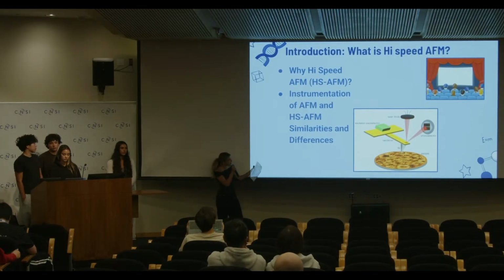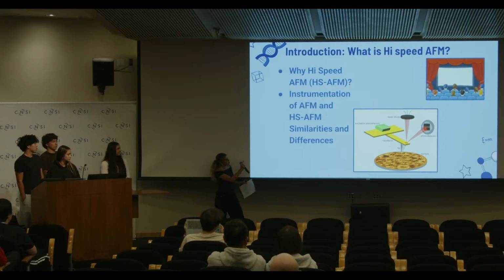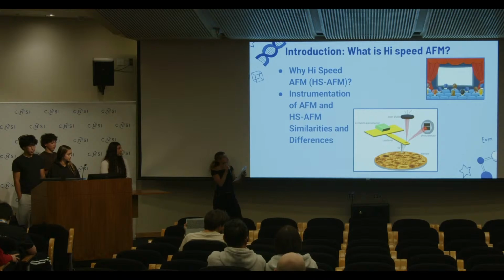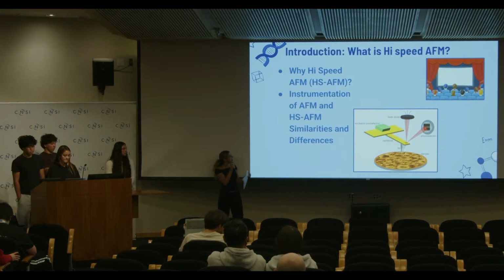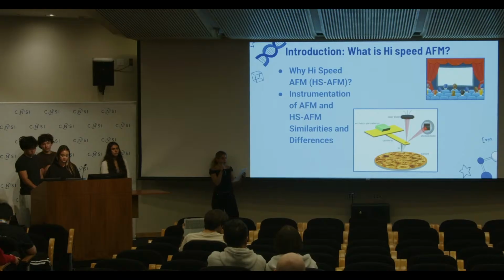And then the photodetector detects how the cantilever moves, measuring the position of the laser, and then the laser shines a beam onto the cantilever to track the movement. So high-speed AFM uses a thinner cantilever than conventional AFM, and that's because it's more lightweight, so you're able to go through the image a lot faster to capture all of the images at a really rapid pace.